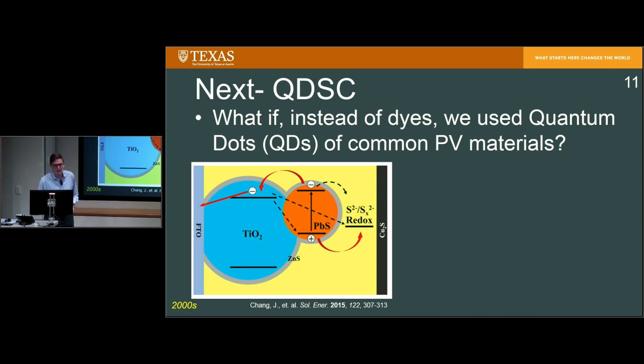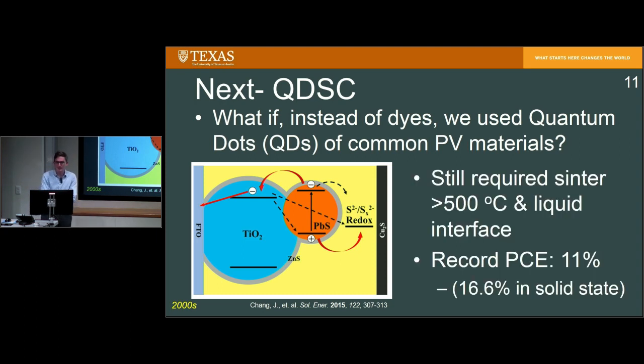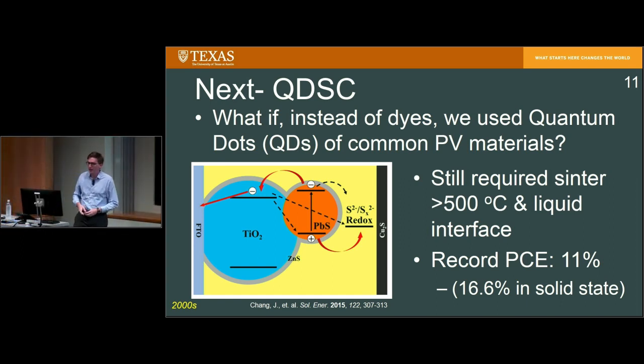And by doing this, we can directly make a solution processed solar cell using the Grätzel cell and get a better absorber, a more electron conductive material that could theoretically have much higher efficiency. Unfortunately, in practice, the liquid junction solar cell didn't really get to a very high efficiency, and it still had some of the issues of the Grätzel cell, although people who took this design and have made solid-state devices with quantum dots have actually gotten to a fairly respectable 16 to 17% efficiency. Actually, this year the record was broken again. So there's still some promise for this type of design.